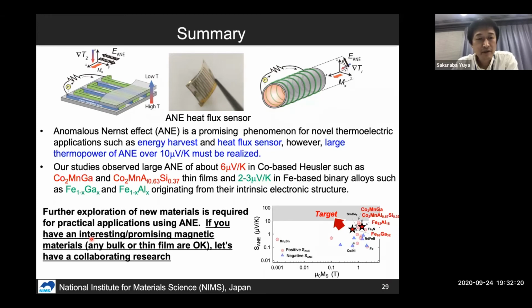And I also introduced several results of the anomalous Nernst effect in several materials. So here you can see the summary of reported thermopower of the anomalous Nernst effect. Actually, no material shows a thermopower over 10 microvolt per Kelvin so far.